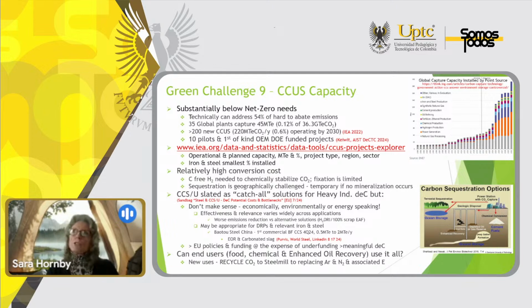There are 200 new projects out there, but that will only add 0.6% to the capture. Relatively high conversion costs are associated with this because you need carbon-free hydrogen to chemically stabilize the CO2, and fixation is limited. And with regard to sequestration, it's geographically challenged. Not everywhere has the capability. For example, Japan can't sequester any CO2 in Japan. They have to send it offshore to the islands.